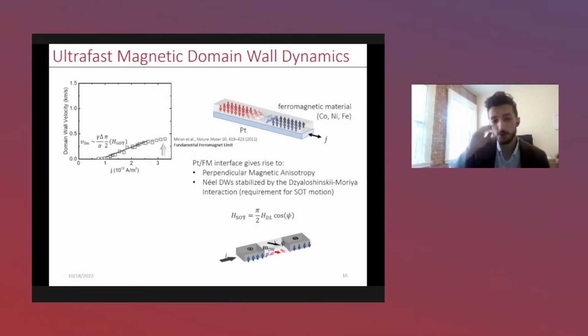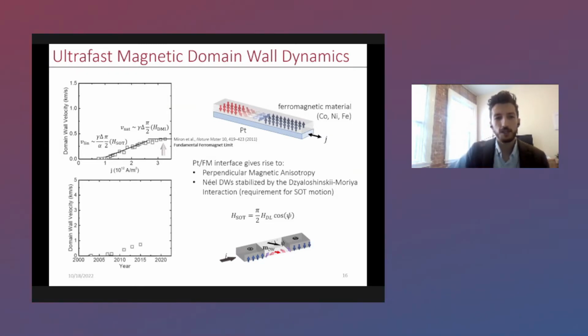But if you take a closer look, what you'll find is if you model this data, you'll see that there's a linear regime where the domain wall responds linearly to the current. This kind of makes sense. The more current you pass through the platinum, the more spins are generated and torque is exerted. But there's also a plateau regime which actually limits the domain wall velocity. This is fundamental to ferromagnetic materials. And it's really this plateau, or the saturation effect, that's limited the propagation speeds of domain walls for a number of years. So where does this plateau actually come from?